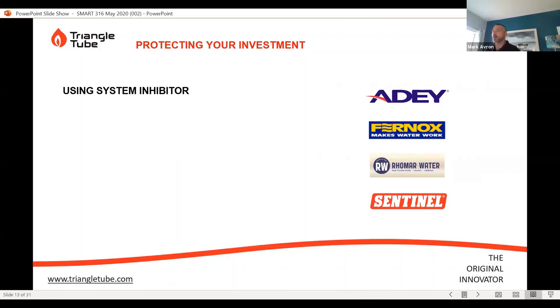This slide, I really want to talk a little bit about using corrosion inhibitors in systems in general, because we're talking about a carbon steel outer tank, having air in the system. Let's say a worst case where you had no oxygen barrier on tubing. There are some systems in different parts of the country with older polybutylene, some of the original PEX, even some of the rubber products used in radiant systems that didn't have an oxygen barrier, and they're still used today. PEX tubing without an oxygen barrier, I would not recommend those products being used with this tank.